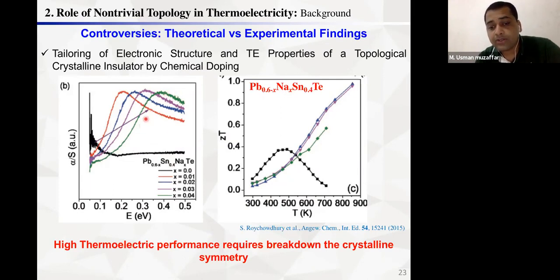So they found that after the doping of 1%, I think maybe 2%, the system is no longer in the non-trivial regime. They make a transition from the non-trivial regime to a trivial regime. This system without the doping of sodium has just a ZT value of 0.4, but in the trivial regime, the system has a maximum ZT of almost 1. So they said that to get a high ZT value, we need to break the crystalline symmetry so that we can get a high Seebeck coefficient and a high ZT.